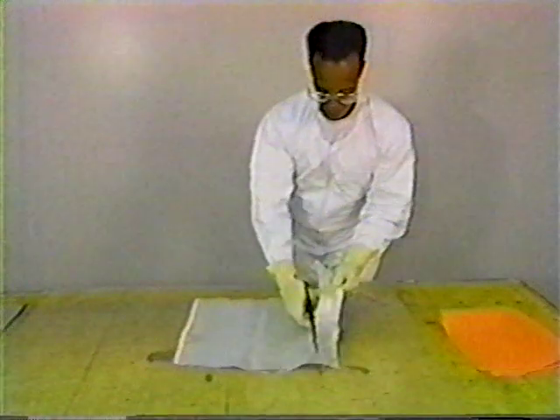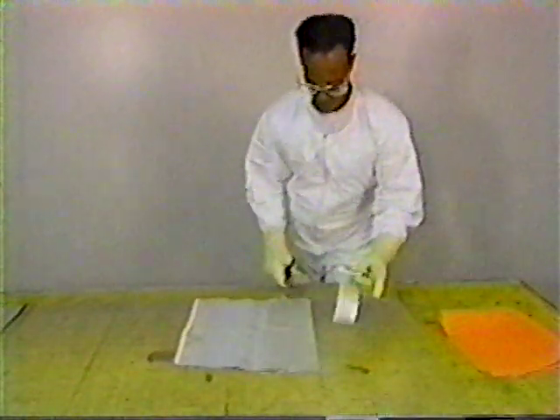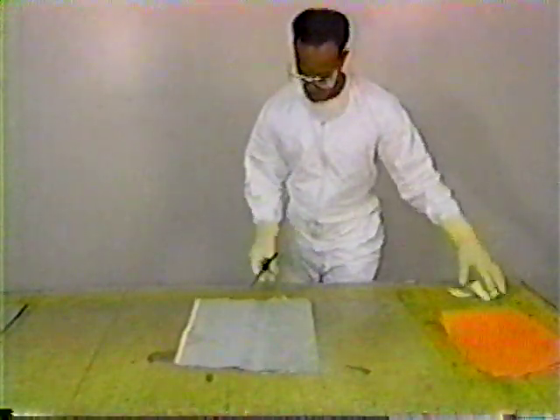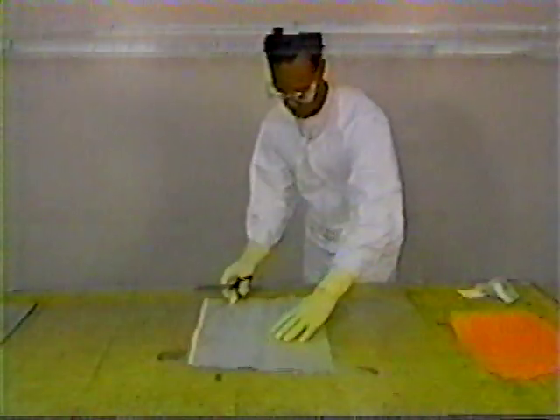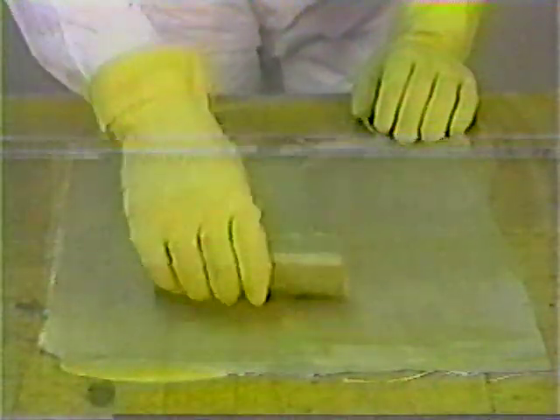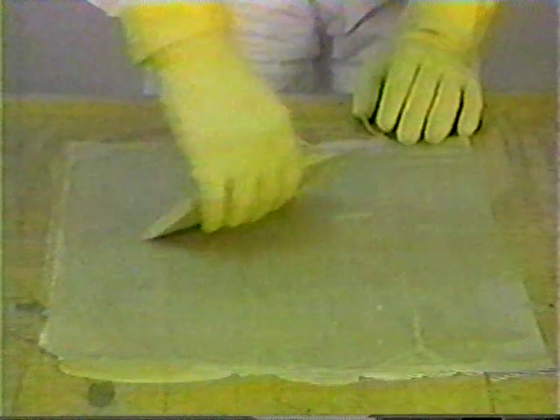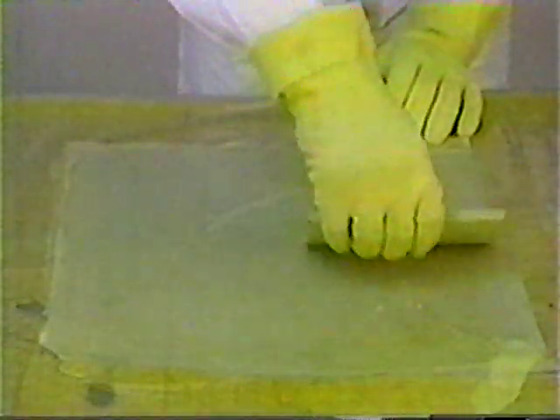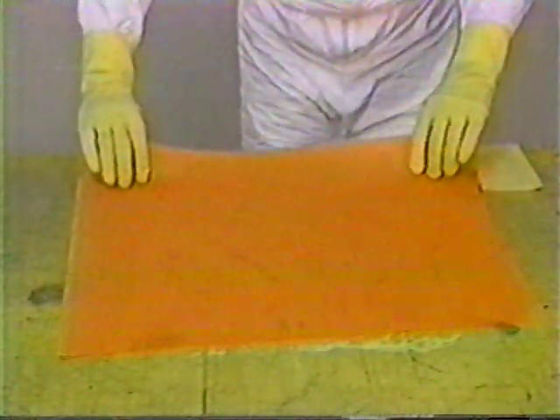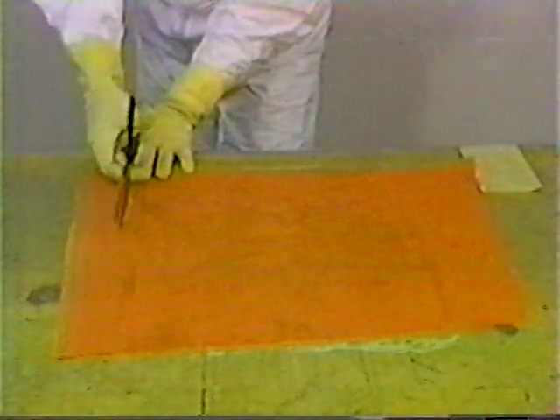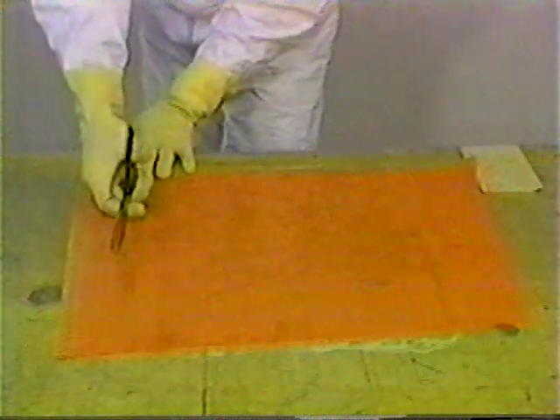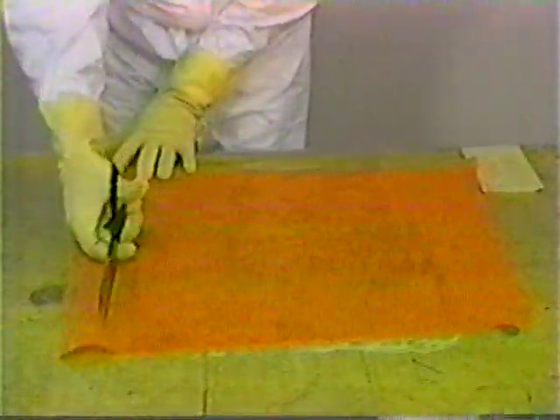Following this, cut a piece of fiberglass material substantially larger than the area of the exposed honeycomb. Thoroughly saturate the fiberglass material with resin that has been mixed according to manufacturer's instructions. Then, place a sheet of peel ply over the fiberglass material, making sure the peel ply has been cut larger than the fiberglass. Then, trim the peel ply so that it is approximately an inch or so larger than the fiberglass material.